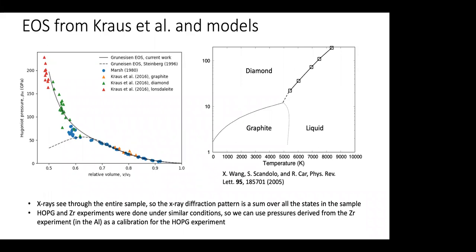In our case, the maximum pressure that we saw in the aluminum ablator was about 100 GPa. And under those conditions, using the equilibrium HOPG or equilibrium graphite Hugoniot, we would only expect to see a pressure of about 80 GPa. And that is at a pressure where Kraus saw some kind of diamond, but only cubic. In our case, though, we're claiming to have seen Lonsdaleite.